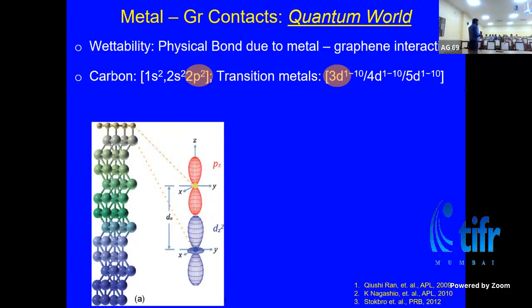Surface states play any role here? Interface states? Till the discussion so far? Yeah. No, I will come to that. So actually, ideally there are no interface states. This is monolayer graphene. All carbon atoms are fully satisfied. The bonds are satisfied. So there's no dangling bonds, so there's no surface state, so there's no interface state.